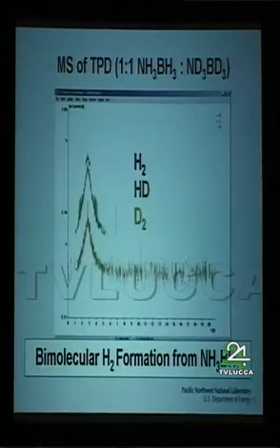So go back, we're going to do the temperature programmed desorption this time, look at the mass spec, and we're not going to ramp it all the way to 200. We just want to look at the reaction in the solid state. We don't want to melt this stuff and have it exchange. So we heat this up. This was, I think, to 80 degrees, and lo and behold, we do get a substantial amount of the mixed isomer species. So we think this is pretty good, strong evidence that it goes by a bimolecular pathway.